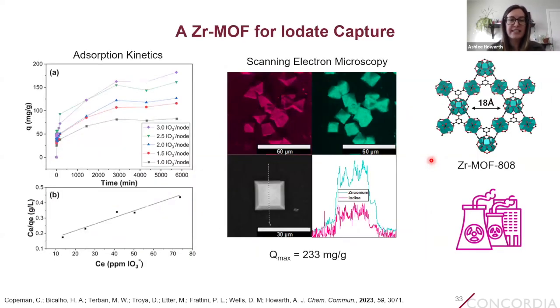So what Chris does is he takes the MOF 808, and he exposes it to aqueous solutions containing iodate oxyanions at varying concentrations, ranging from 1 to 3 iodate oxyanions per node. So saying per node is kind of like saying per mole of material. From these adsorption kinetics, we can construct a Langmuir plot, which can tell us about the maximum adsorption capacity Q in our material, which tells us that MOF 808 has a maximum capacity of 233 milligrams of iodate per gram of MOF, which is actually one of the highest capacities that's been reported for any adsorbent material in the literature so far.